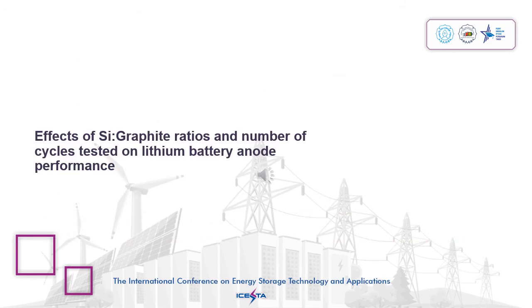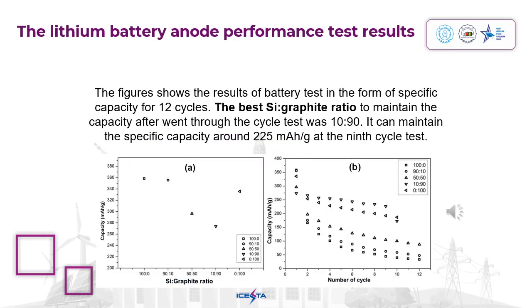Effect of silicon and graphite ratios and number of cycles tested on lithium battery anode performance. The figures show the results of battery tests in the form of specific capacity over 12 cycles. The best silicon and graphite ratio to maintain the capacity after going through the cycles was 10/90. It can maintain a specific capacity around 225 mAh per gram at the 9th cycle test.